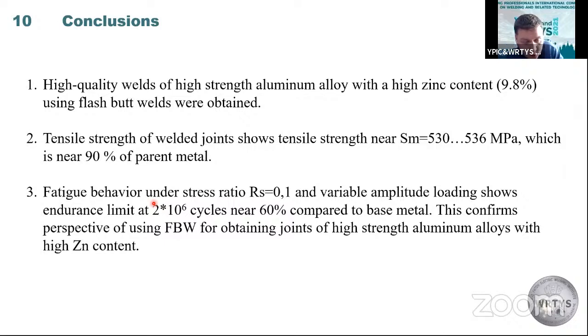Tensile strength of welded joints shows near 90% of the parent metal, and fatigue behavior under stress ratio 0.1 and variable amplitude loading shows an endurance limit near 60% at 2 million cycles. This confirms the perspective of using flash butt welding for obtaining joints of high strength aluminum alloys with high zinc content.